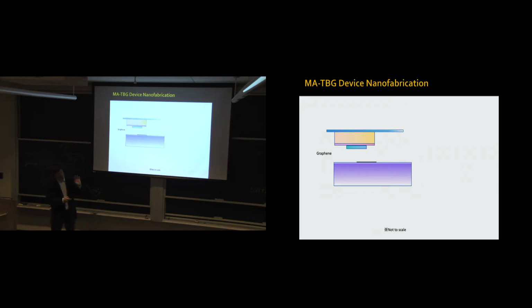But the thing we do that's a little special is we position our hexagonal boron nitride halfway on top of the graphene sheet. Now I bring my boron nitride down, and I tear the graphene piece in two.